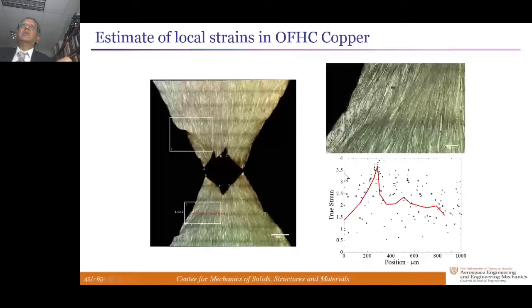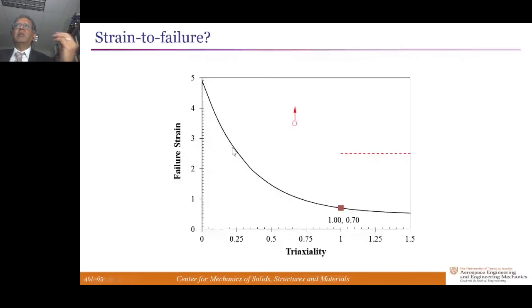So if you want to use a strain to failure criterion, making global measurements is almost irrelevant because locally the specimen does something completely different. And we've been able to observe local strain levels on the order of 3 to 3.5 with moderate triaxialities and about 2.5 with high triaxialities without failure. This is what I mean by late in the game. You have to allow the material to strain to such levels and therefore develop constitutive models applicable to such strain levels before fracture occurs at all.